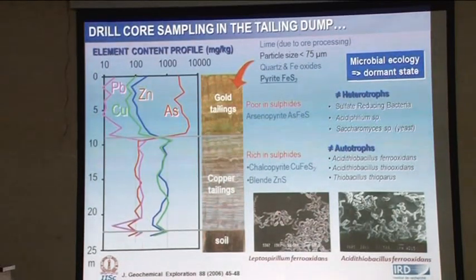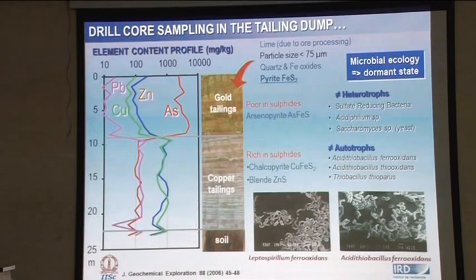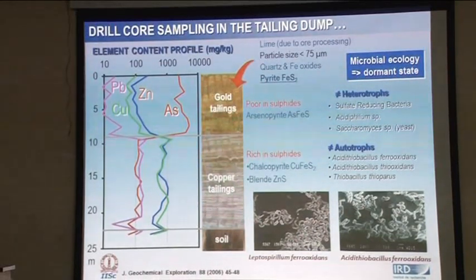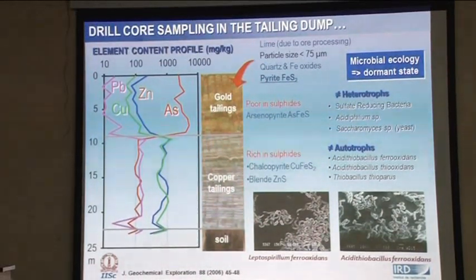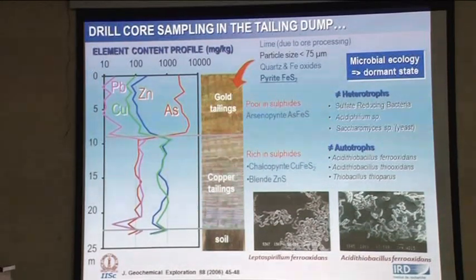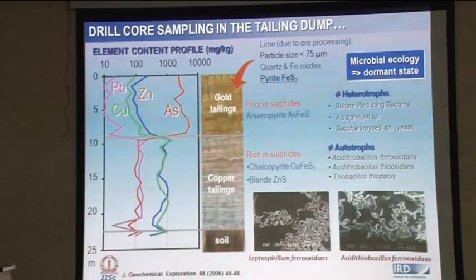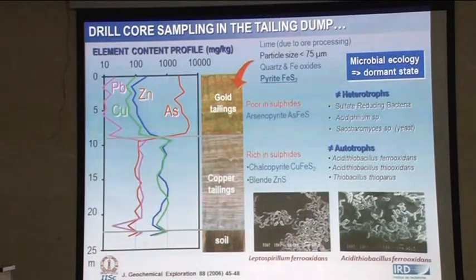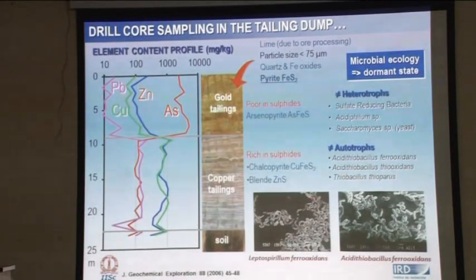We collected samples for every meter, and we analyzed the geochemical constituents of that. And as you can see, all these elements are present there. As can be expected, because of the gold being present in arsenopyrite, you have higher concentration of arsenic there. But as far as the copper tailings, you have the other elements, that is copper, lead and zinc.